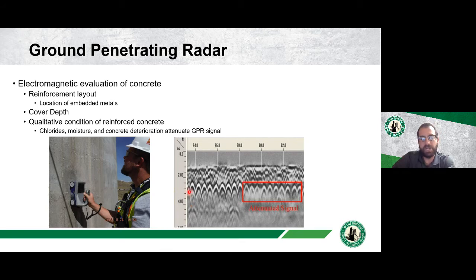So here's a typical GPR scan, and you can see these white hyperbolas. These are the individual rebar, and they're nice and bright here, and then they're nice and faded over here. So this is an area of attenuation. These signals are weaker than these signals. So weaker signals identify that maybe there's salts or moisture or deterioration of the concrete occurring here.